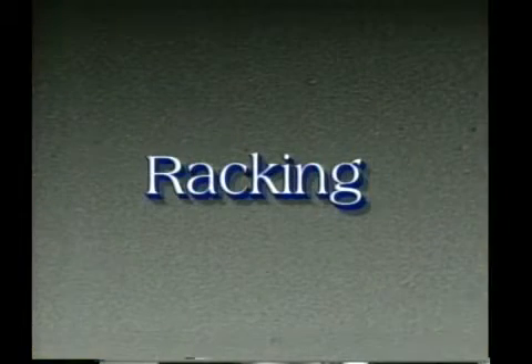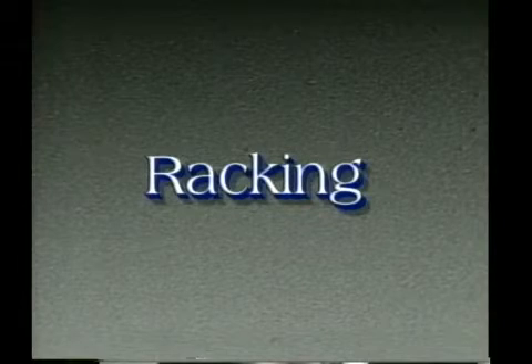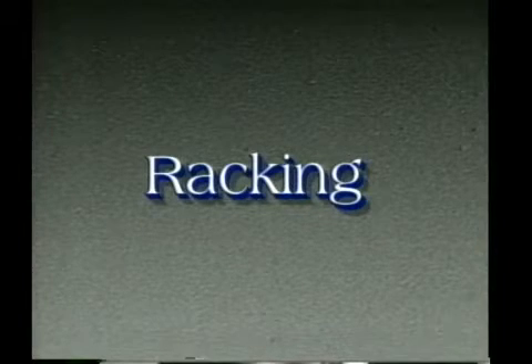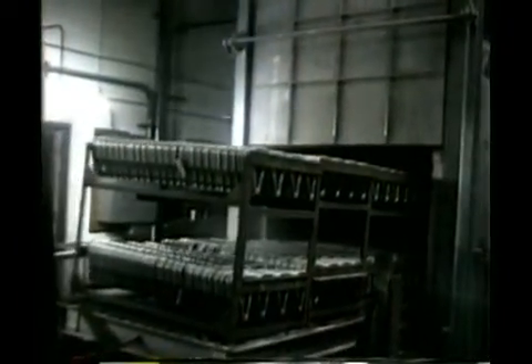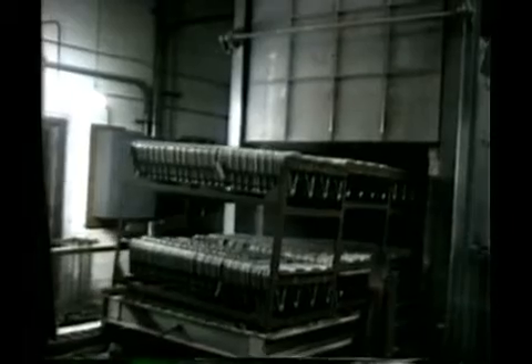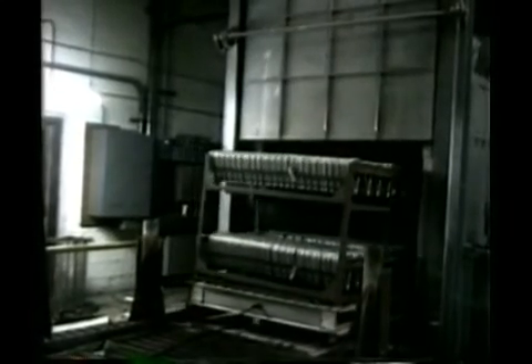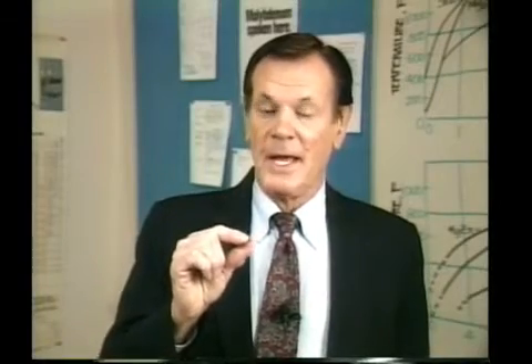To ensure that parts are heated and quenched properly, the correct racking of parts is essential. When racking parts for a solution heat treating operation, care must be taken to ensure that the parts are properly spaced so good airflow will allow the parts to reach the solution heat treating temperature evenly in the shortest period of time. An illustration of good racking practice is shown here. With the exception of extremely small parts, excessive nesting, stacking, or part contact should be avoided whenever possible.